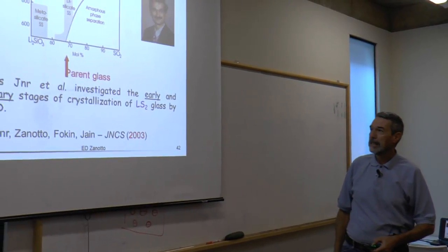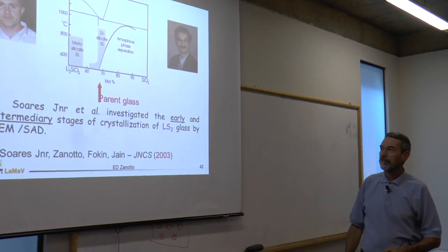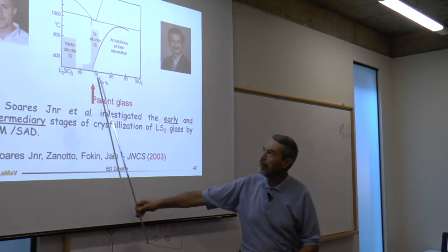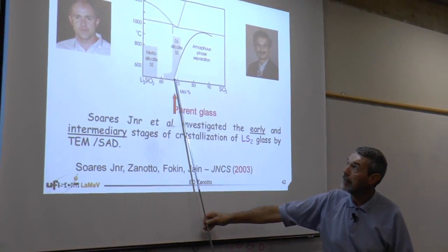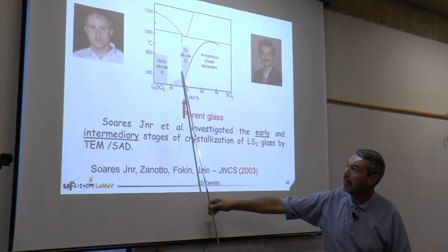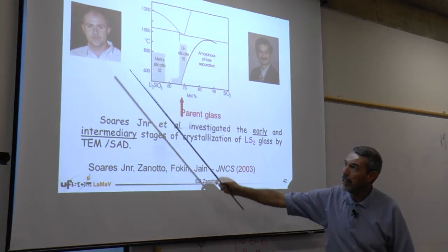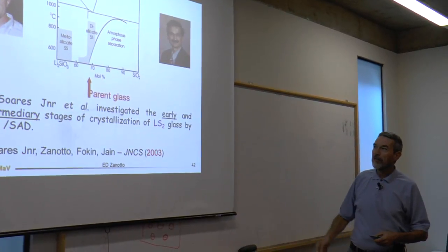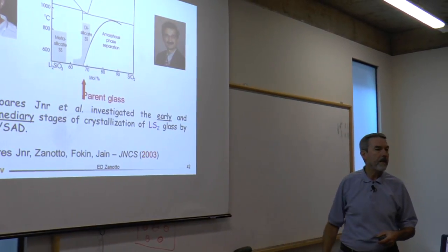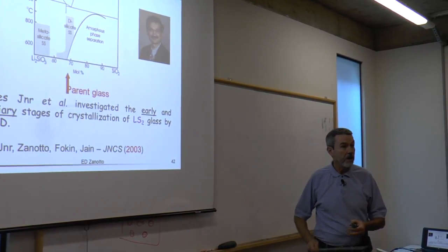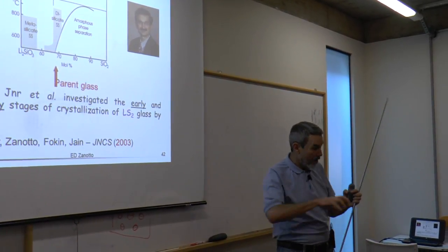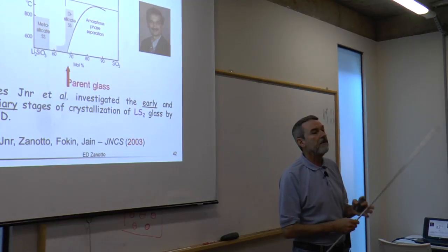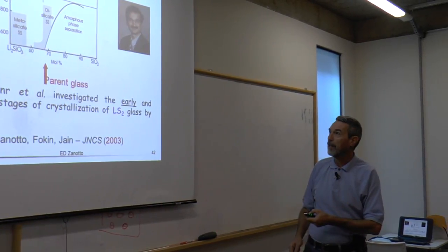Anyway, we did a very interesting study of early stages of crystallization. We took a stoichiometric lithium disilicate glass, and Paulo was my student. He went up to work with Professor Himanshu Jain at Lehigh University because they had, at the time, extremely good electron microscopy facilities. We wanted to look at the very early stages with electron microscopy to find out if any metastable phase was forming in this particular system.